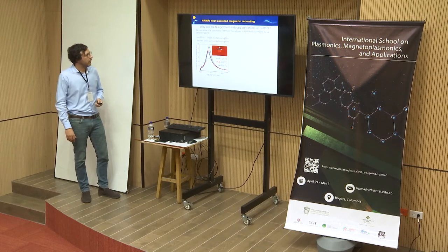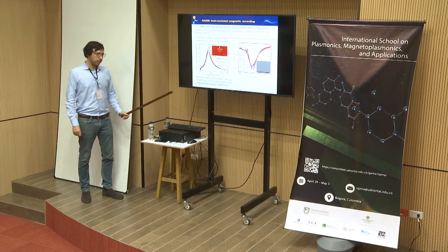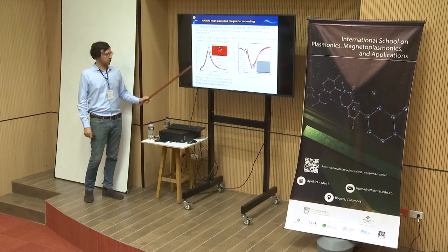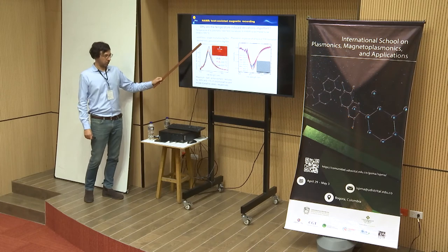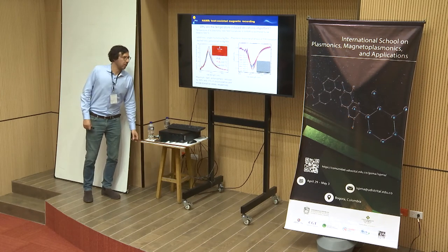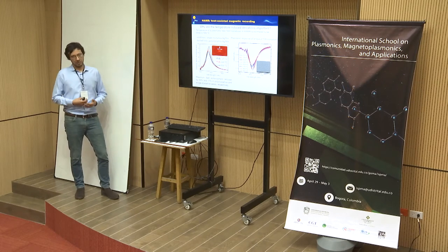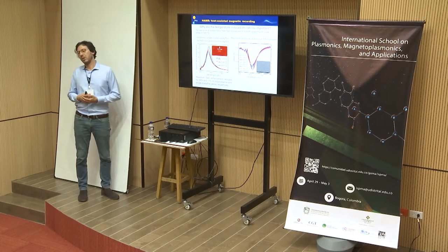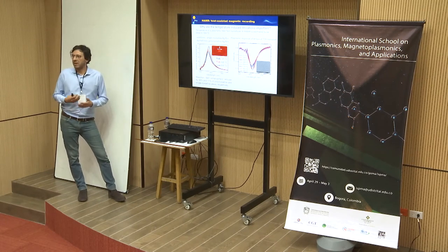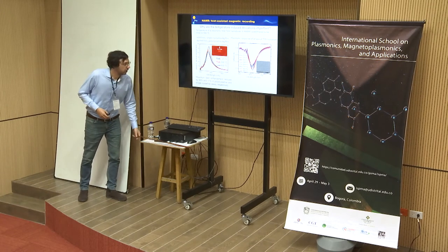So this is, again, an example of what happens at high temperature. For example, you can see that the resonant field enhancement really changes if we consider room temperature or 300 or 600 degrees C. It is also interesting to see that polycrystalline metal films behave differently than single crystals. Usually single crystals have much higher resistance of their optical properties to temperature. And here again an example.